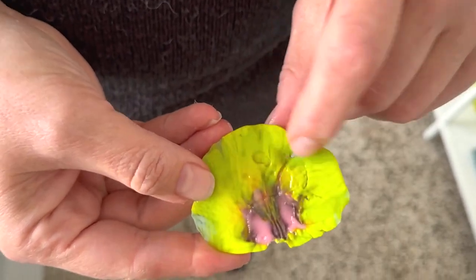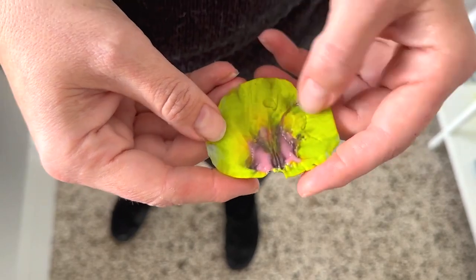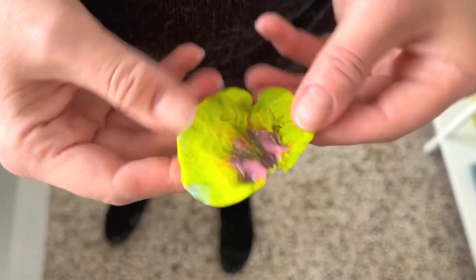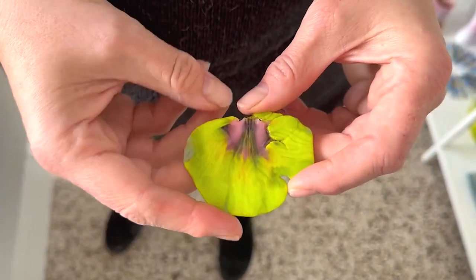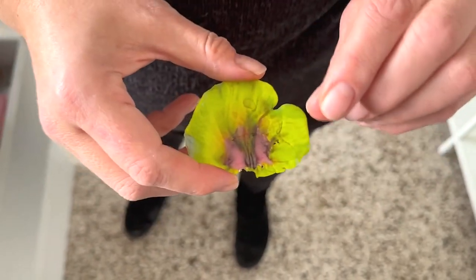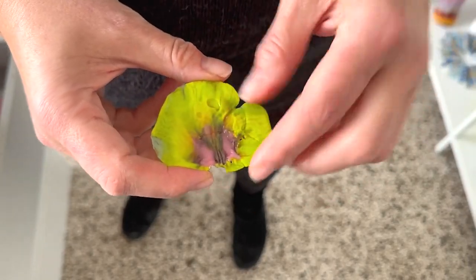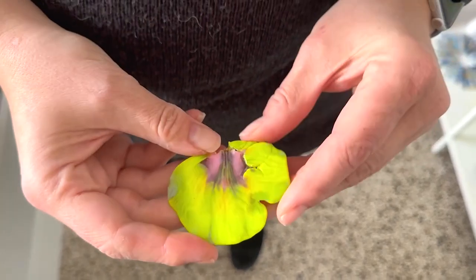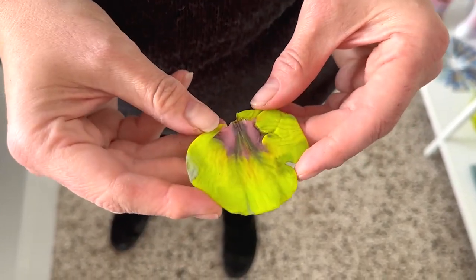There are massive pot marks, and the kiln wash did kind of ball up in these areas. But it's interesting — it shows you can press things in a microwave kiln. I'm thinking maybe a thin kiln shelf at the bottom and a kiln shelf at the top with some little posts might be better than fiber paper underneath, and maybe a lighter kiln wash on the shelf. We'll carry on experimenting, but you can see you can get beautifully thin wafers in a microwave kiln.